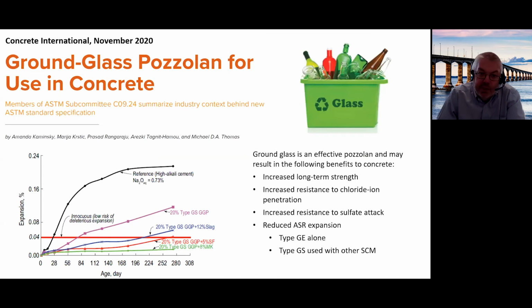For those of you who are interested, a recent paper just appeared in the last issue of Concrete International on the use of ground glass pozzolan in concrete, which does show that ground glass is an effective pozzolan, doing all the things you expect of a pozzolan: increasing long-term strength, increasing resistance to chloride ion penetration, increasing resistance to sulfate attack, and reducing ASR expansion. Type GE glass can do that on its own, whereas type GS glass, if you want to control ASR, needs some help from another SCM, whether that's fly ash, slag, silica fume, metakaolin, or a natural pozzolan.